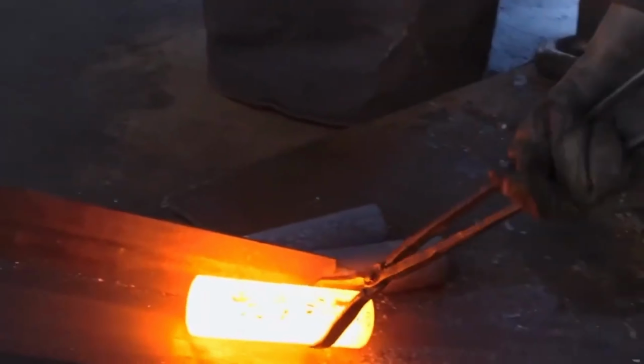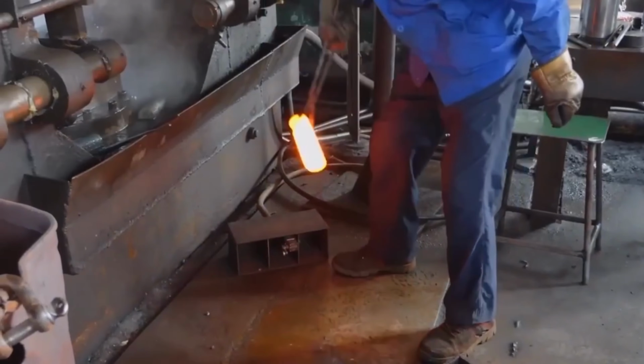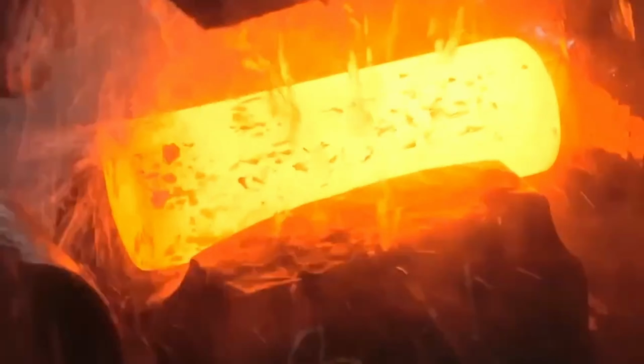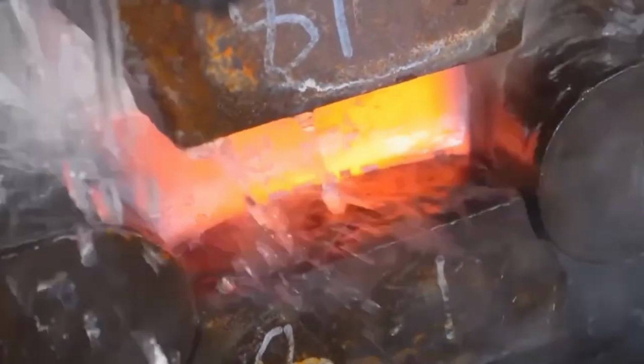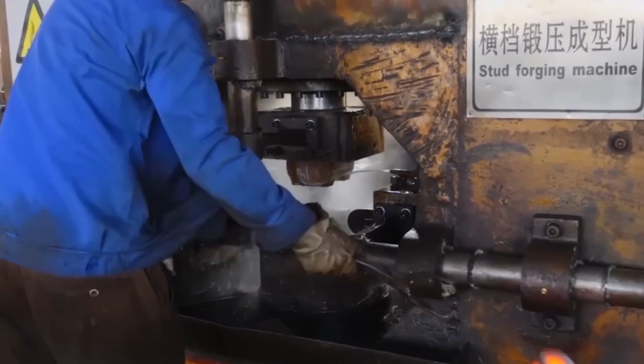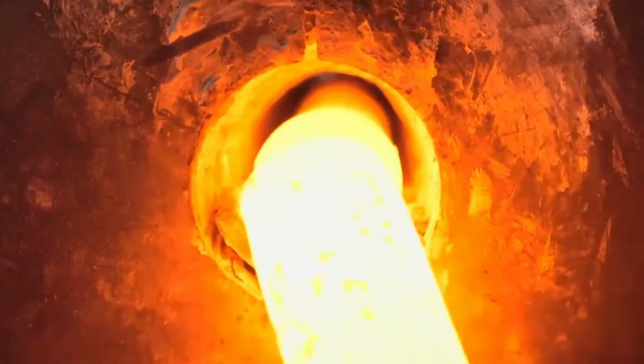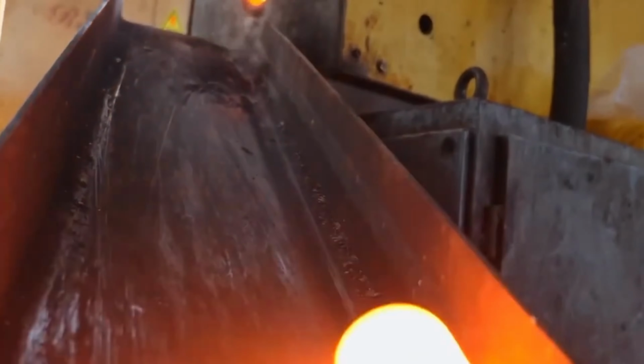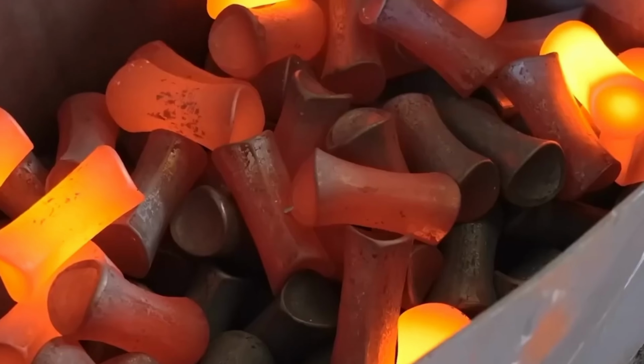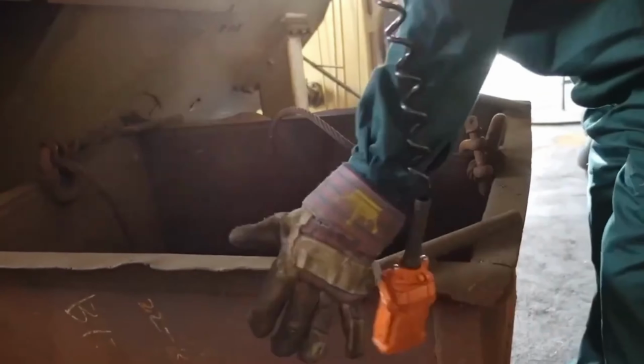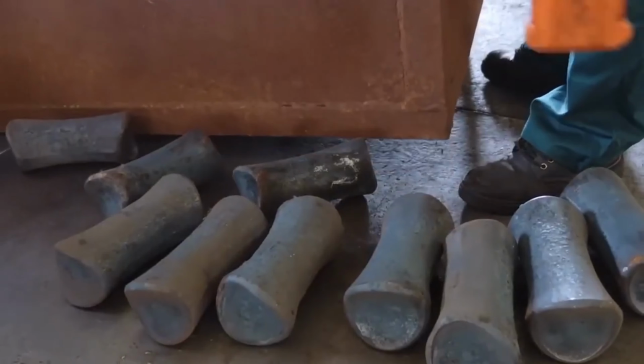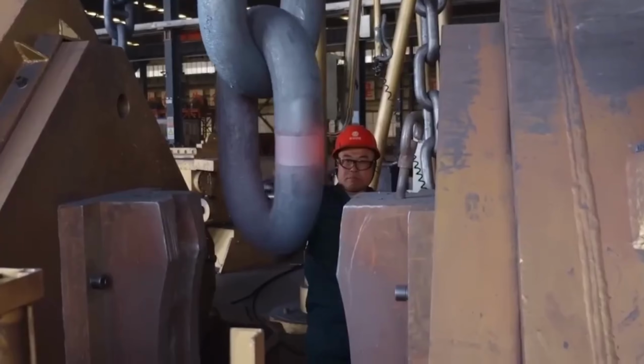Depending on the grade, chains undergo quenching and tempering. First, the chains are heated inside massive furnaces to precise temperatures, often over 900 degrees Celsius, until the steel's microstructure transforms. Then the glowing chain is rapidly cooled in oil or water, a process called quenching, which hardens the steel significantly. However, quenched steel alone is too brittle for industrial use, so the chain undergoes tempering. It's reheated to a lower temperature to return toughness and ductility while maintaining high strength.